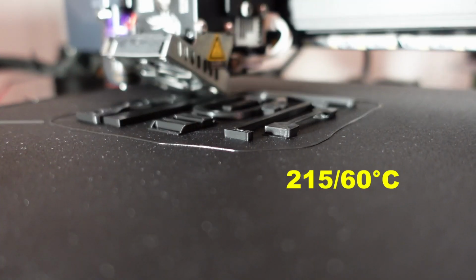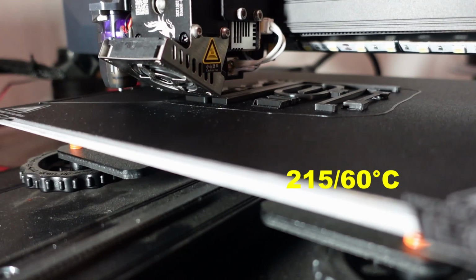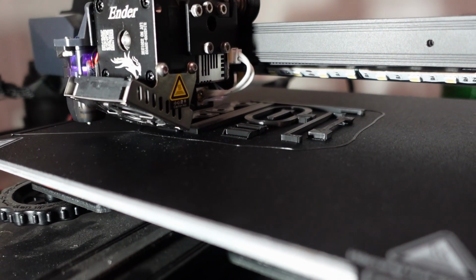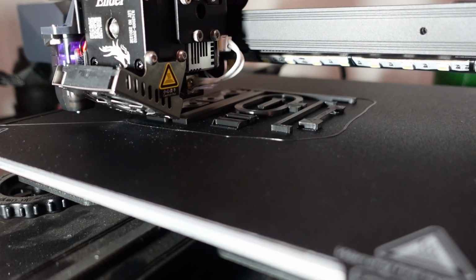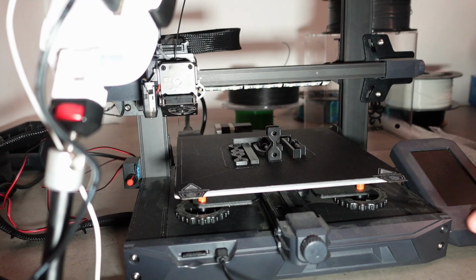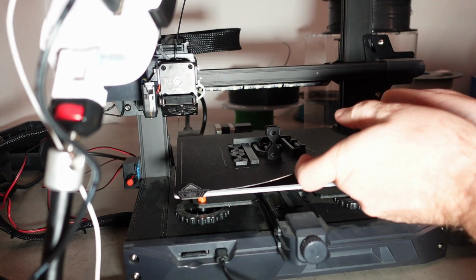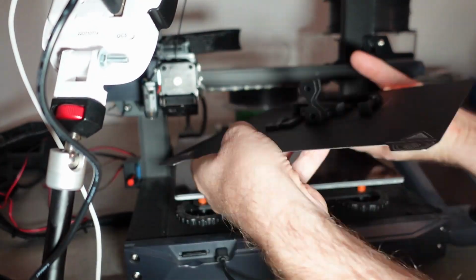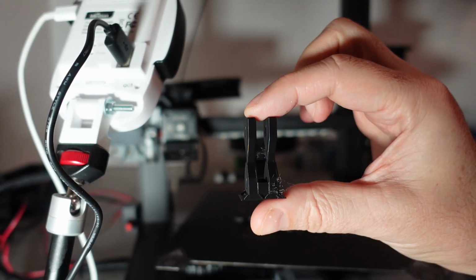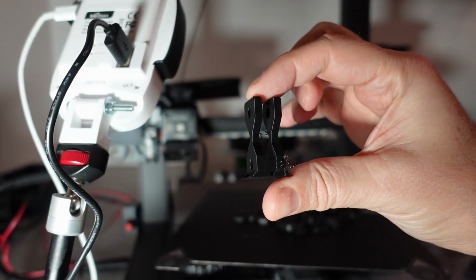All test subjects will be printed at once. After 1 hour and 25 minutes everything is okay, and I hope it will stay like that because this will be an overnight printing. Good morning, and the printing was finished without problems. I can see that stringing was present even on this temperature, but very minimally.